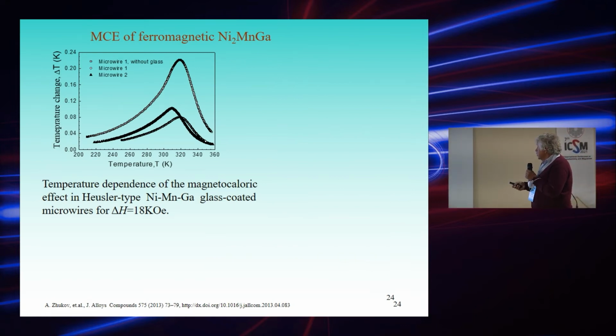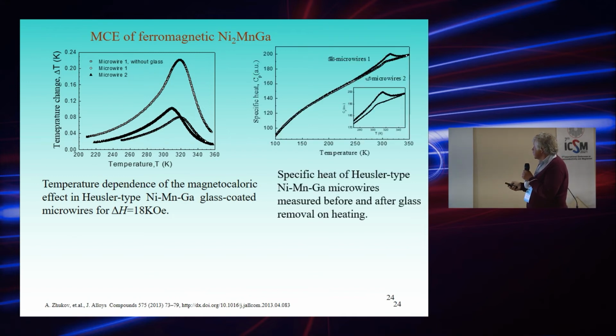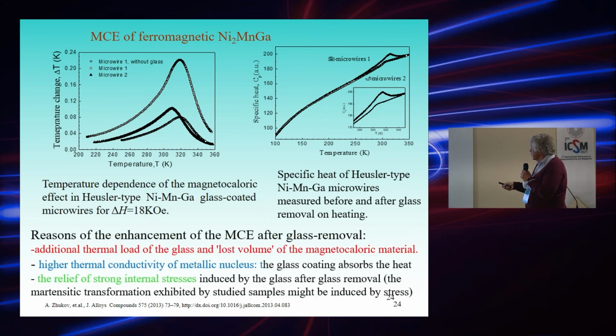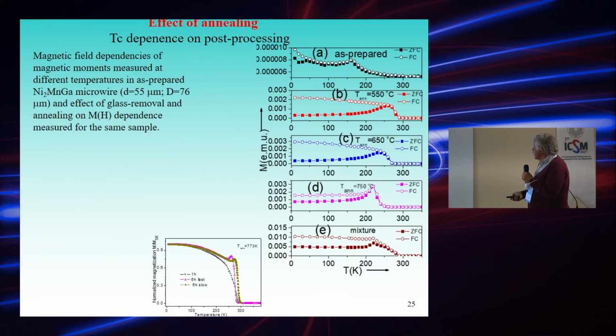And just to mention that in similar materials we measured the magnetocaloric effect, like the change of temperature, but in the setup of our collaborators in Russia, and we also observed this magnetocaloric effect in a different kind of nickel manganese gallium microwires. For example, we also tried to remove the glass, and we found the effect was larger somehow.